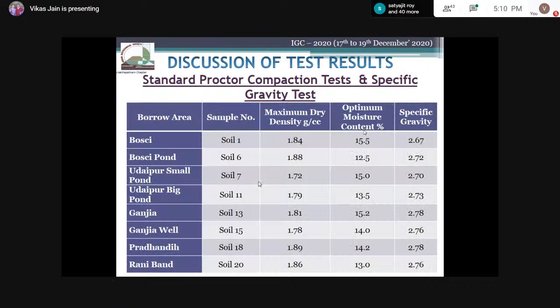These are the results for the Proctor compaction test. We selected 1 soil sample from each of the borrow areas. We have done the compaction test and specific gravity test. From these test results, we could recognize that the MDD of all the samples varies from 1.72 gram per cc to 1.89 gram per cc, and the OMC varies from 12.5% to 15.5%.